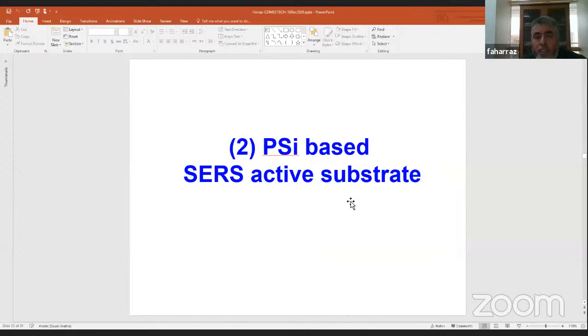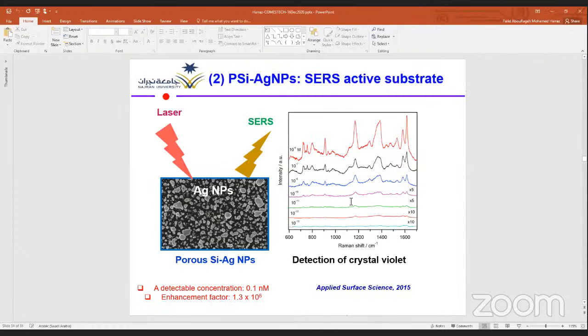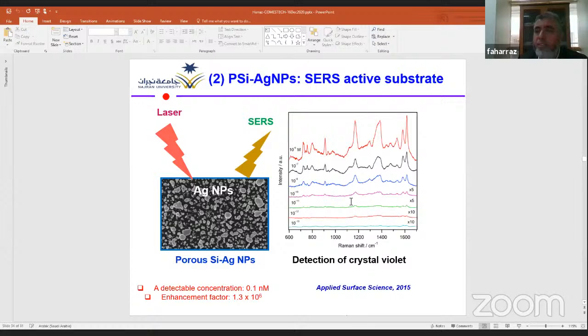The second example concerns the utilization of porous silicon as a surface enhanced Raman scattering active substrate. This technique is very interesting and fascinating to sense various target analytes at very low concentration levels. We modified porous silicon with silver nanoparticles with a very simple chemical process, and we got an active substrate for sensing and detection of crystal violet dye.